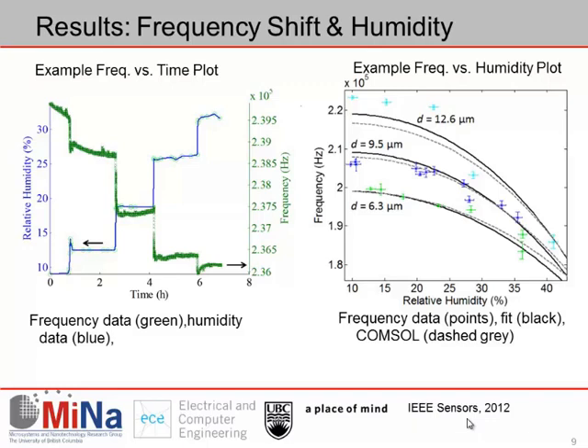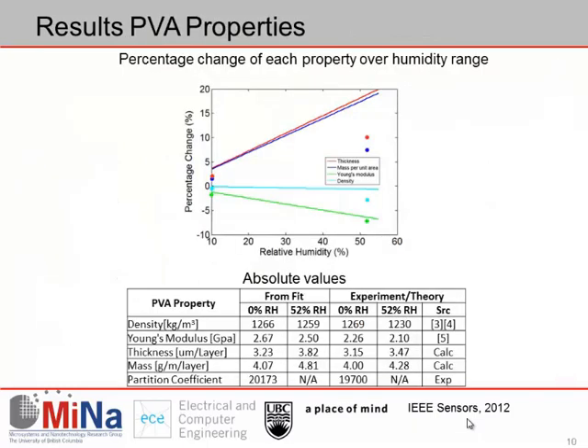The plot on the right shows all the data that we collected with fit curves, those are in black, and results from a COMSOL model presented by Christoph Sielmann in the aforementioned work. So if we take the results from the fit curves that were shown here, we can make a plot that looks like this. This describes the percentage change of each of our properties of interest, so thickness, mass per unit area, Young's modulus, density, as a function of RH. The lines correspond to what we got from the fitting function, and the points correspond to those which we would have expected based on previous reports and our own measurements.